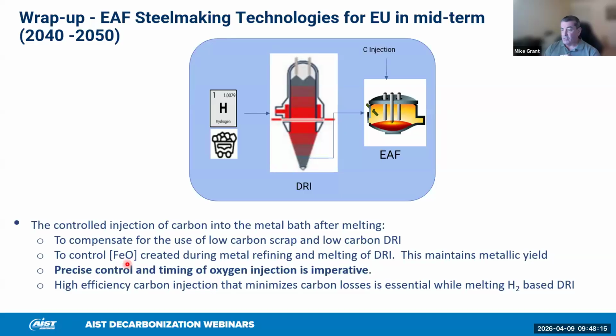And in fact, really, if you can control the FeO content in your slag, you can control the foaming. And this means precise control of carbon injection and oxygen injection to balance.